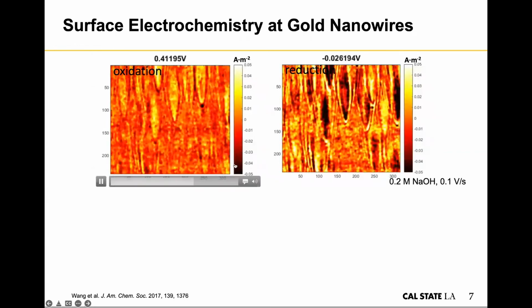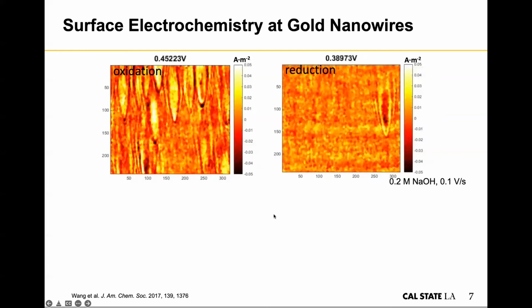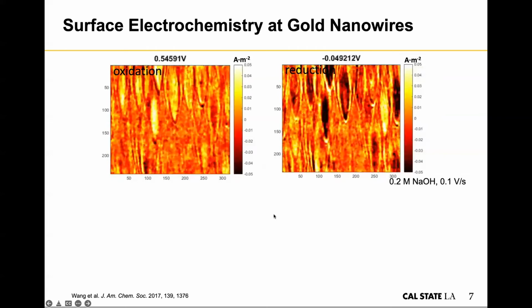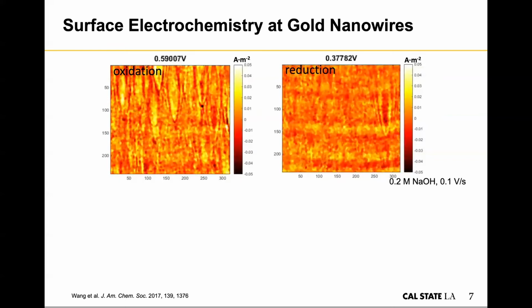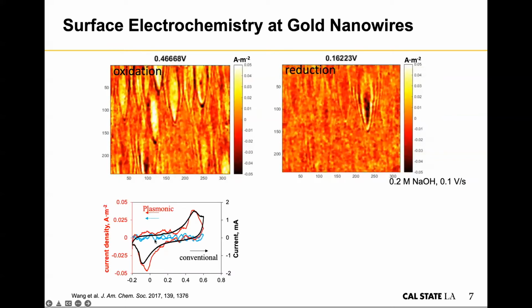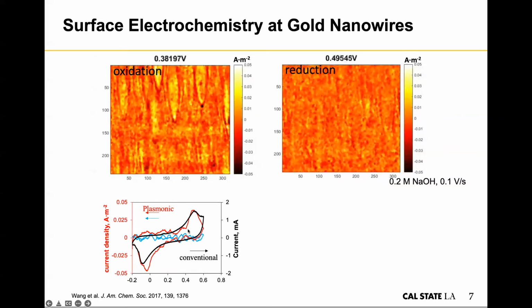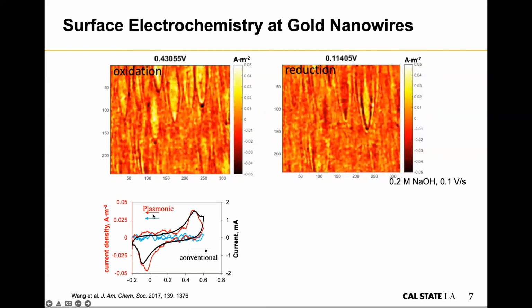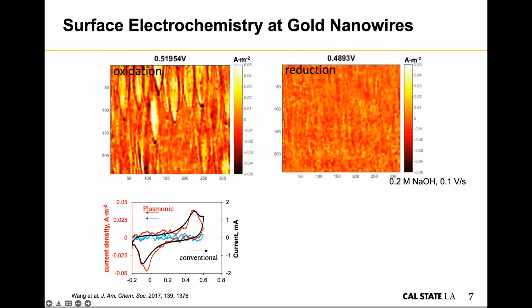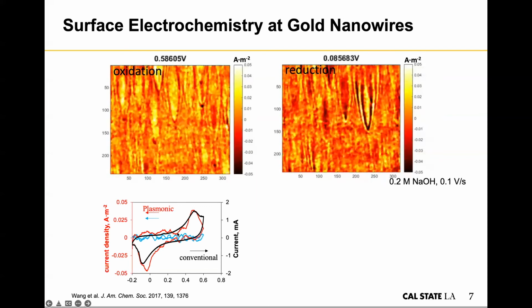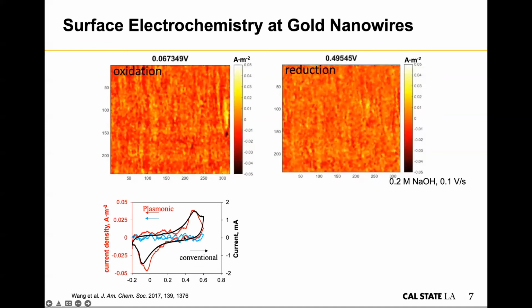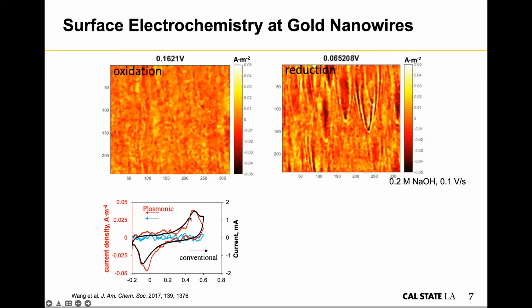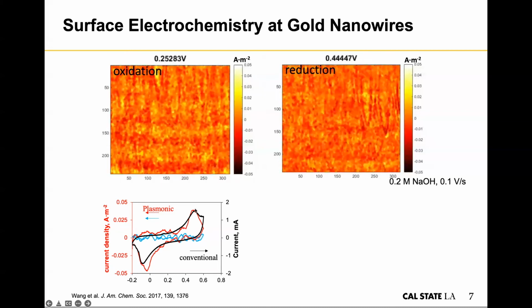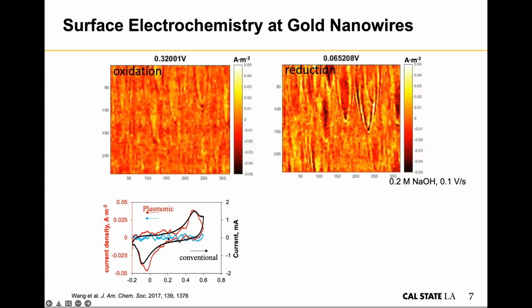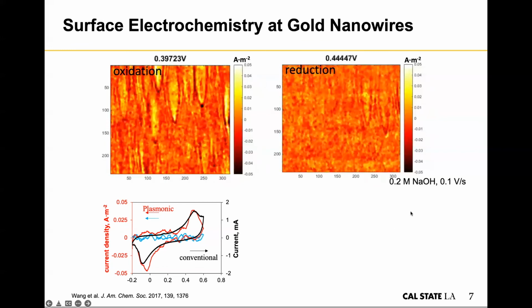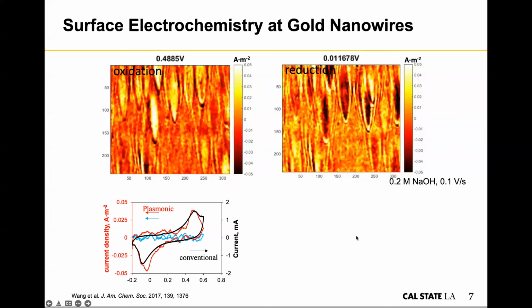And we can compare the SPR signal to the potentiostat CV, which is collected directly from the potentiostat that induces the voltage and records current. So here, the black one is the conventional CV, and the red one is the plasmonic CV. I believe that the red one is the plasmonic CV with nanoparticles, and the blue one is without particles. So you can see that without particles, we don't have any current, and with particles, we see the oxidation and reduction peak, and the position overlays very well with the potentiostat CV, demonstrating that we can actually visualize the surface reaction at individual nanowires.